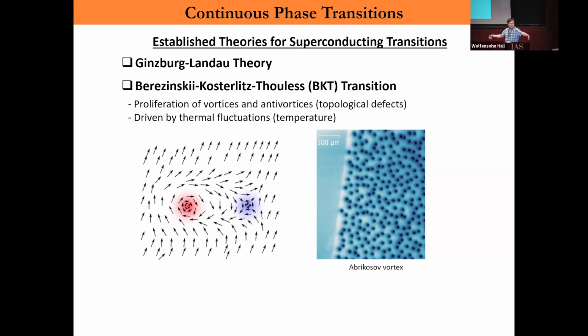In the ordered phase, in a superconducting phase, you now expect to have this proliferation of vortices and anti-vortices. This is, for example, in the ordered spin system in two dimensions, you can have these vortices and anti-vortices. In the two-dimensional superconducting phase, you can have this because of vortices. So when you increase the temperature for the 2D superconductors, we expect vortex and anti-vortex pairs to emerge quickly, and then they destroy the superconducting state.